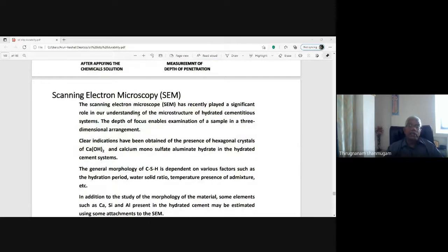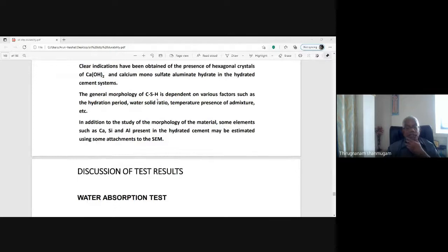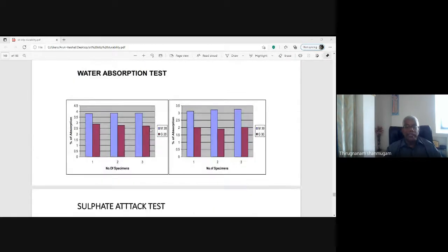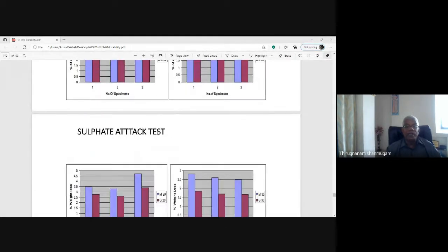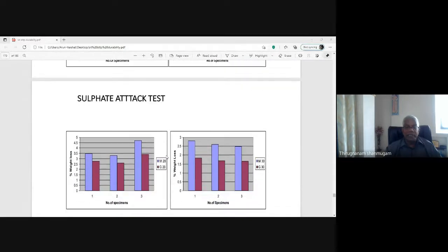Scanning electron microscope imaging of the failure surface is carried out. Clear indication has been obtained with the presence of hexagonal crystals of calcium hydroxide and calcium monosulfate aluminate hydrate in the hydrated cement system. The generated morphology of calcium silicate hydrate gel is dependent on various factors such as hydration period, water solid ratio, etc. The discussion of the result was also performed the same way with the G20.